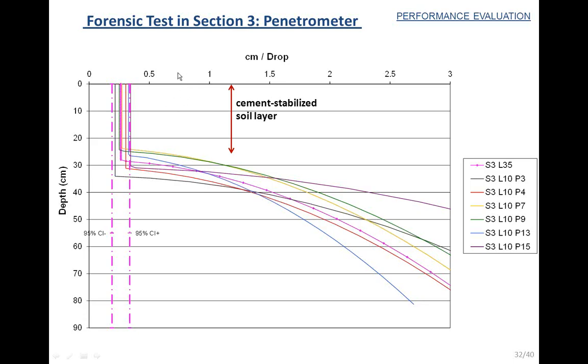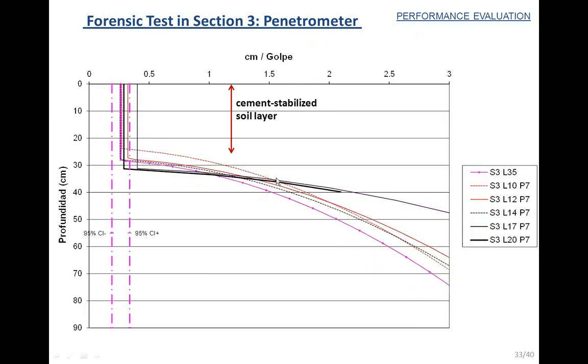So we were expecting a higher level of penetration, but in fact we were surprised to see that the soil seemed to be in good condition. So we were certainly not expecting this result. And we also did the same thing, but in the transverse direction. Here these different lines correspond to different transverse positions. For example, here line 10 is the center of the wheel path, and you can see that in the center of the wheel path, this dashed red line, the penetration is the same as in the non-loaded area, and the only point where we obtained higher penetration was here in line 17.